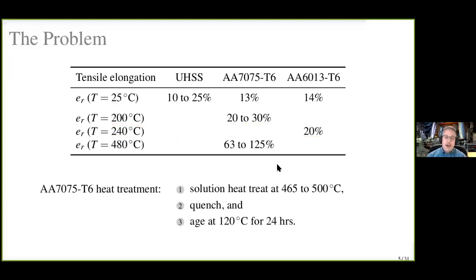Now, the problem is that the heat treatment for 7075 to get that T6 condition usually involves 3 steps, typical steps for any heat treatable aluminum alloy. We do a solution heat treatment at 465 to 500 degrees Celsius. That's right about where the hot forming temperature is. We have to quench it rapidly. Most of the high strength aluminum alloys are somewhat quench sensitive. If we don't quench them rapidly, we won't be able to age them to high strength. So we have to have that rapid quench. And then the aging for 7075 is typically about 120 degrees Celsius for 24 hours.